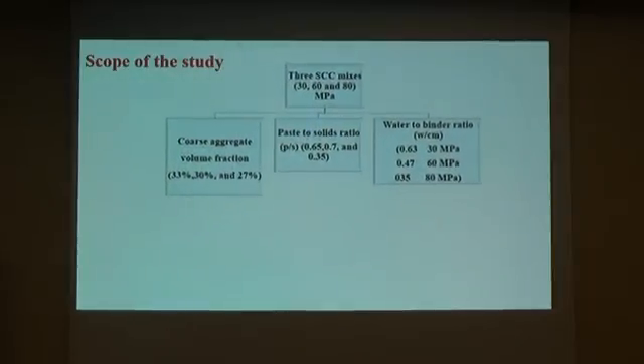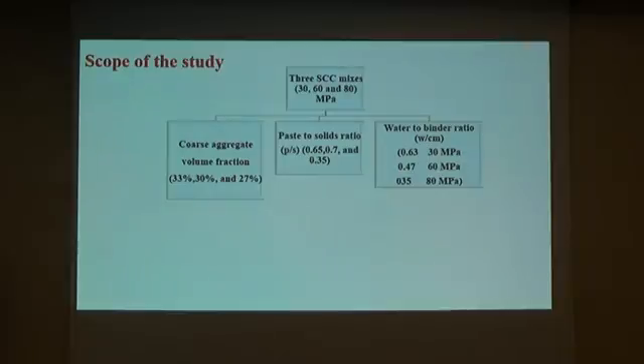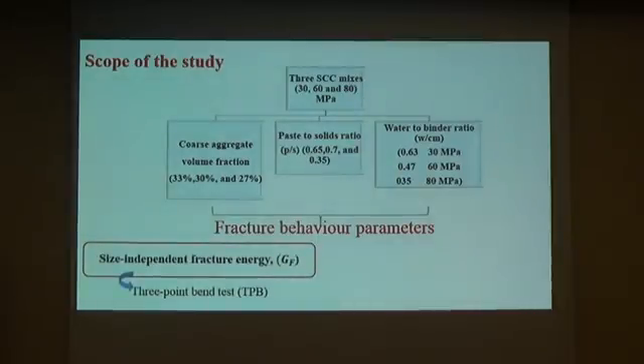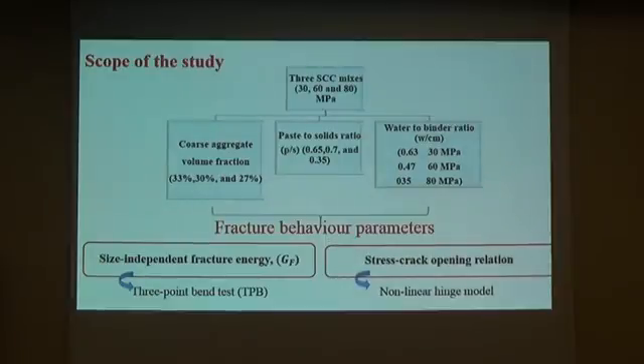Scope of this study: there are three self-compacting concrete grades, 30, 60, and 80 megapascal, and these mixes differ by coarse aggregate volume fraction. There are three volume fractions of coarse aggregate, three paste-to-solid ratios, and also three water-to-binder ratios, depending on the grade of strength. Then the fracture behavior parameters, as I mentioned before, size-independent fracture energy by using the three-point bend test, and the stress crack opening relationship by using the nonlinear hinge model, are obtained.